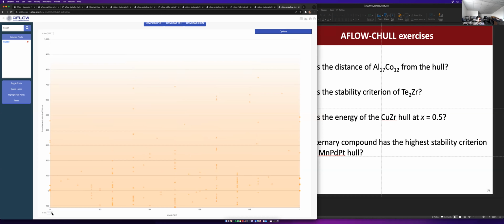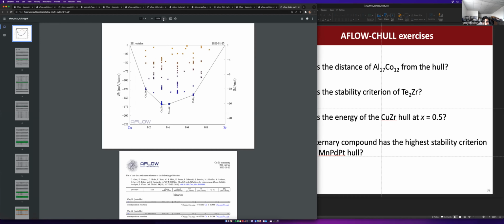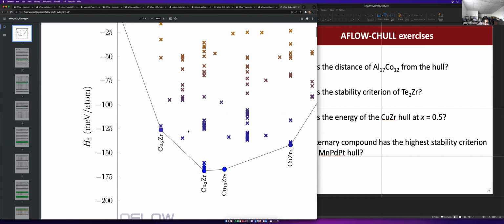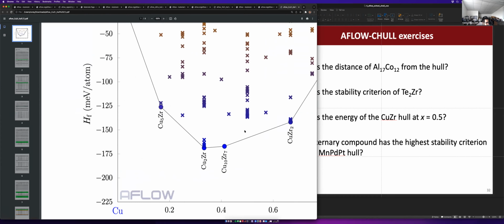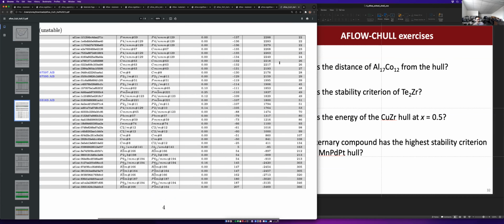But you could see what values we were getting at. You can also look at the PDF, which might give you a little better perspective. Yeah, this is a little better. You can see here that we were looking at 130, so that sits around here. The convex hull value is at around 160, 165. So we're looking at about 30 or 40 meV per atom. That's the distance you're looking for, roughly. If you had the command line, you would be able to get the value exactly, but that's more or less what we're looking at. Actually, you should be able to get that value from the distance to the hull here.